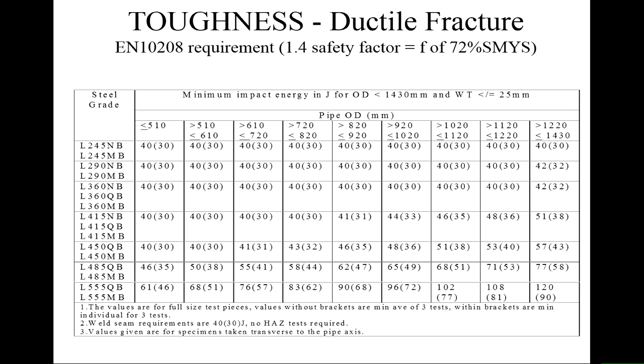So what you see here is a range of values that you can use in design, and then of course you've got to take into consideration that these things are going to be welded. So requirement 2 here says weld seam requirements, and the weld seam requirements are similar to the requirements that you get for a low strength steel. So you hope that the weld is more ductile than the higher strength steels that you've got in these particular cases here.